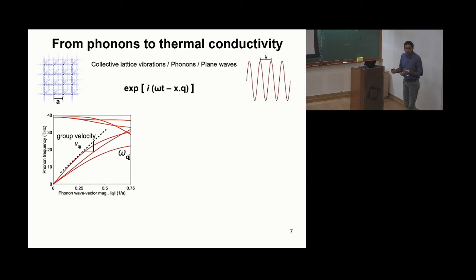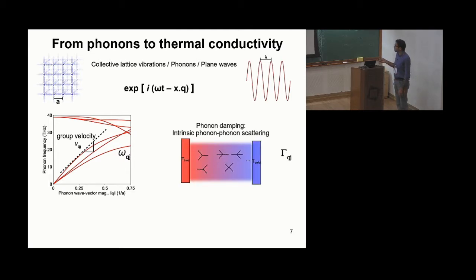I introduced phonons as the eigenmodes of a perfect harmonic lattice, but in reality no crystal is perfectly harmonic. There are always anharmonicities to the potential. Whenever you have anharmonic components to the potential, the eigenmodes necessarily have to interact and undergo damping. These damping mechanisms are driven by what are called phonon-phonon scattering processes. So in a solid, because of the anharmonicities, you can have interactions among 3 phonons at a time, which is a 3-phonon process. You can have interactions among 4 phonons at a time, and so on.